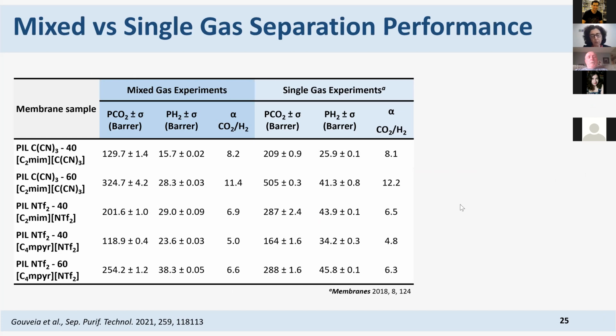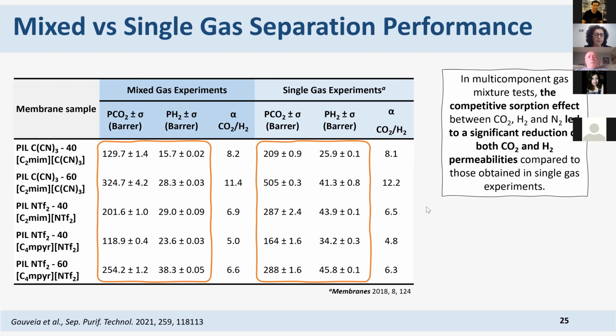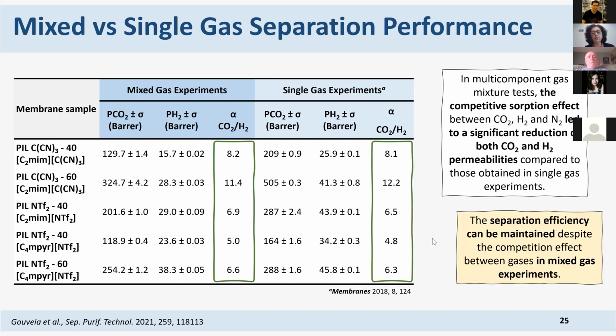The first thing that we can see here for the permeation of gases is that the permeation is much lower in mixed gases than it is in single gases, especially due to the competitive sorption effect, since this is a dense membrane. And this can be observed for CO2 and also for hydrogen. However, in terms of selectivity, the selectivity is kept when we work with mixed gases. And so this is very good news. Let's see now the performance of these membranes.